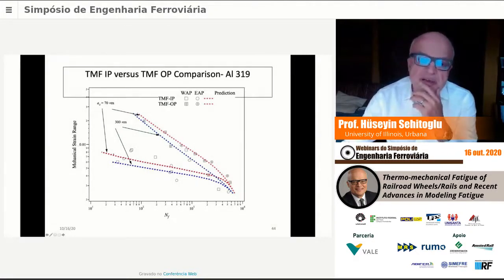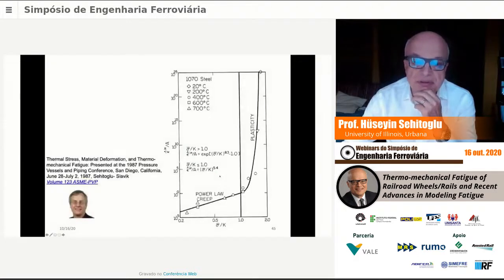These are some experiments we did, and some of the predictions we had at the time. And this is fatigue life. This is mechanical strain range. This turns out to be that in this particular class of materials, the in phase is more damaging than the out of phase. So we've looked at that in the case of cylinder heads.